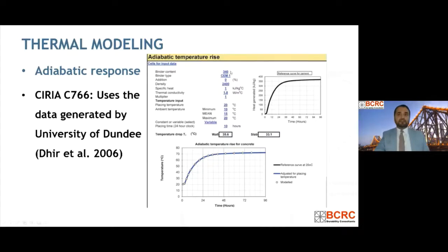Yeah. So you put your binder content, whatever the binder content you have in your concrete mix. You put the binder type, whether it's 100% GP cement, whether it has some fly ash in it or it has slag in it. You put that binder type in it, and then you put the addition, like what percentage you're putting in it. And you can easily predict this graph, right, which is the adiabatic response.